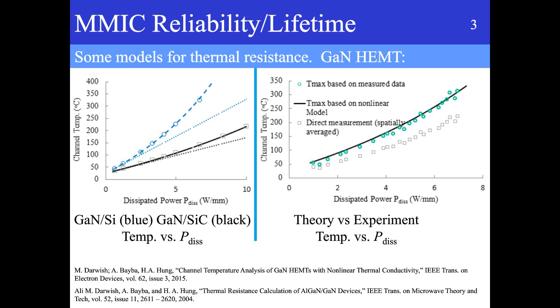So if you look at the lines, you will find that the dotted line is the linear prediction, the one that assumes that the thermal conductivity doesn't change with temperature. And then the dashed line is the one that takes into account the change in thermal conductivity as you heat up the device. So if you look at, let's say, 5 watts per millimeter, you see quite a significant difference between the dashed line and the dotted line. So any time you're dissipating large amounts of power, you absolutely need to consider the nonlinearity of the thermal conductivity, and you cannot really just go with the simplistic equations that pretend that it's linear. On the right, you see theory versus experiment for some of the equations that you just saw earlier.